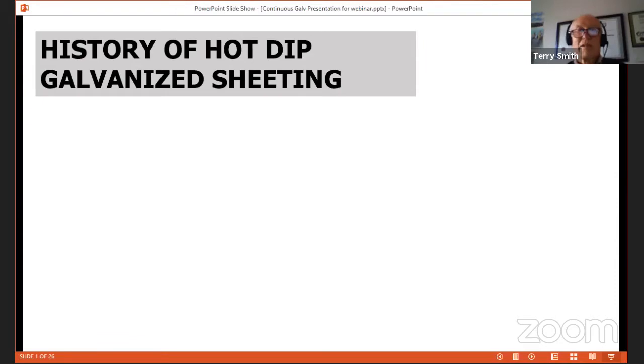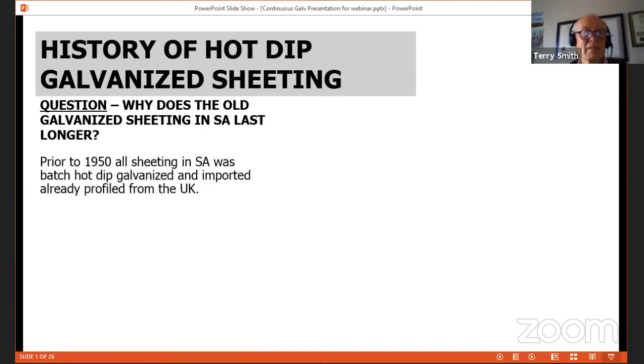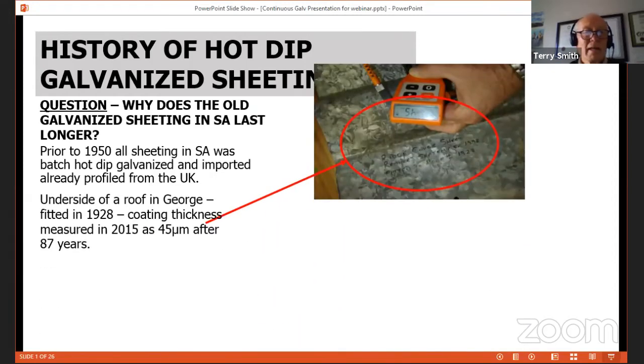Okay, good afternoon, ladies and gentlemen. I'm going to talk a little bit about starting off with the history of hot dip galvanized sheeting. Question, why does old galvanized sheeting in South Africa last longer? And I'm sure some of you have seen some of this. Prior to 1950, all sheeting in South Africa was batch hot dip galvanized and imported, already profiled from the UK. Here's an underside of a roof in George, fitted out in 1928. Coating thickness measured in 2015 as 45 microns after about 87 years.